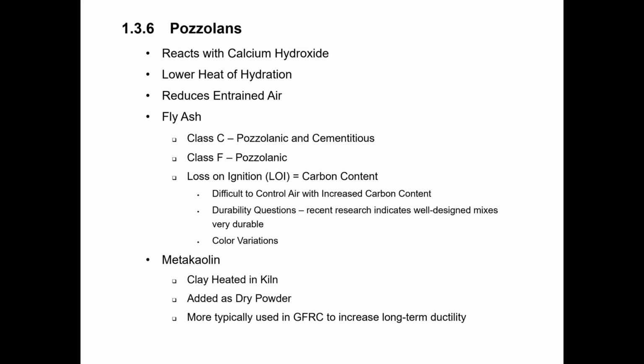It also starts reacting with the water, and then it does produce a hardened stone-like mass. It just takes it longer to do that. Because it takes it longer to do that, we get less heat that's generated from using fly ash. And so in some instances, that's an advantage. There may be certain applications where we don't want a lot of heat generated during the concrete curing process. But then for precast operations, generally we do want heat generated. We want that hardening process to move along at a fairly good rate so that we can gain our stripping strength and then turn the form over and pour it again the next day.